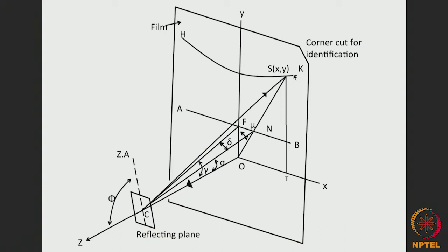So, for different values of gamma we will have different hyperbolas here from left to right. Now, if we consider the same value of delta on the plus side here or the minus side over here, and if we draw lines through equal values of delta, then they will form another series of hyperbolas from top to bottom.